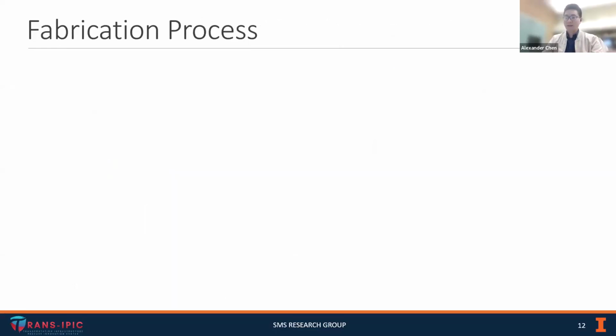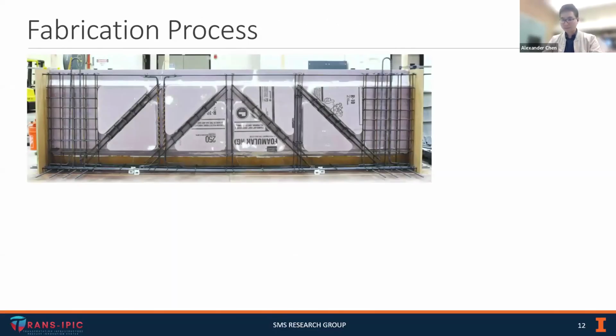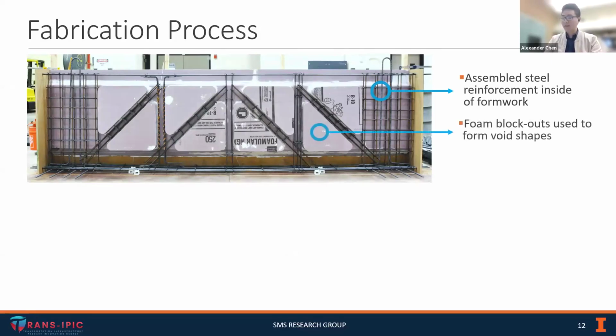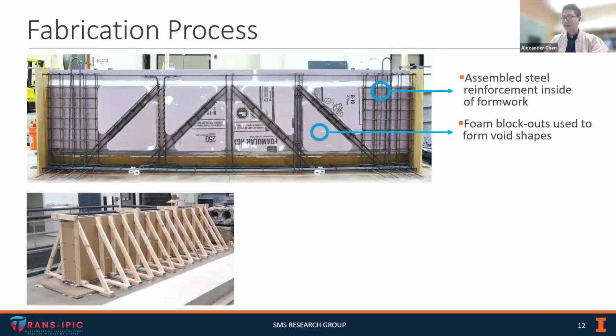Now I want to talk a bit about the fabrication process. The first step was to assemble the reinforcement inside of the formwork, and this was done by tying all the bars together with rebar ties and supporting them on top of rebar chairs. We used 8 of these triangular foam blockouts to form the shape of the voids in the truss. Then we closed everything up and added a series of braces along the outside to support it against the concrete lateral pressure.